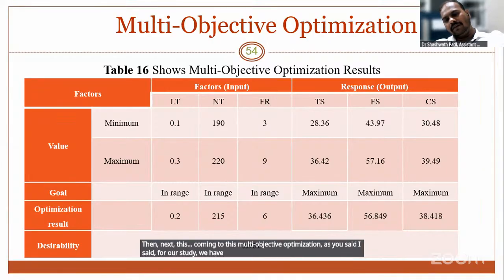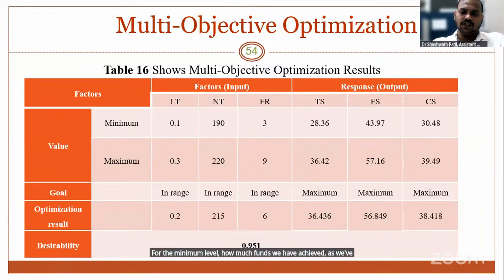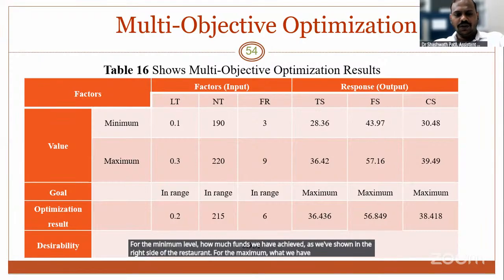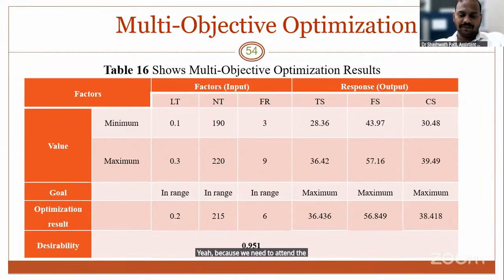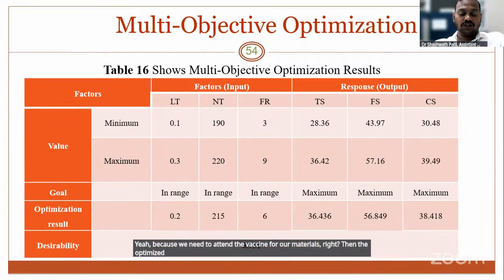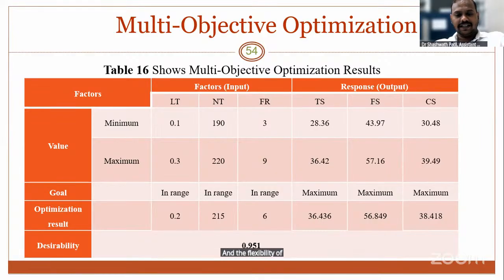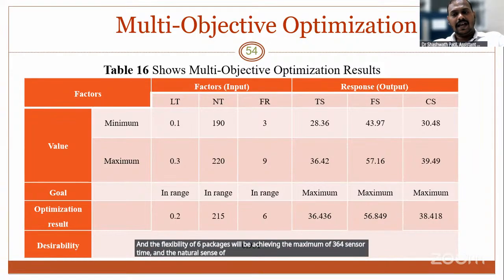Next, coming to the multi-objective optimization, for our study we used three input parameters and three output parameters. The minimum and maximum levels of the output parameters are shown on the right side of the response output. We kept the inputs in range, whereas for the responses we targeted the maximum strength, because we need to attain the maximum strength for our material. The optimized results show that the software suggests a layer thickness of 0.2, nozzle temperature of 215, and filler ratio of 6%, which gives a maximum of 36 for tensile strength, 56.8 for flexural strength, and 38 for compression strength. This shows a desirability of 0.9.